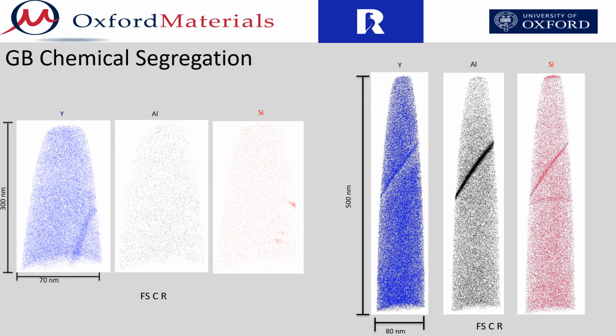Preliminary grain boundary analysis has demonstrated significant chemical anisotropy at grain boundaries, both between different types of specimens and between different grain boundaries of the same specimen. Shown in this slide are 2 grain boundaries with significantly different chemical segregation behavior, coming from the same lift-out bar.